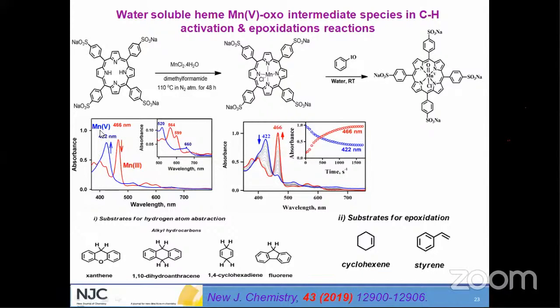So this 422 peak you cannot get just like that. The manganese goes to some other oxidation state, and we then tested whether it is +5 or +4. A very simple way to test is with a simple substrate like triphenylphosphine or thioanisole. Triphenylphosphine will only take oxygen, and if it does, the reaction is quantitative. You should get final manganese +3, which you can trace by UV-visible spectrum, and it should form quantitatively, that is 100% or 99%, if the reaction is 100%.